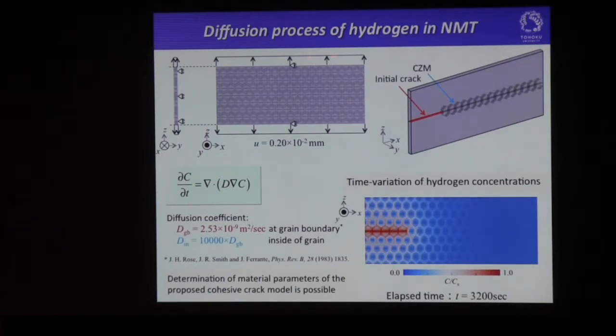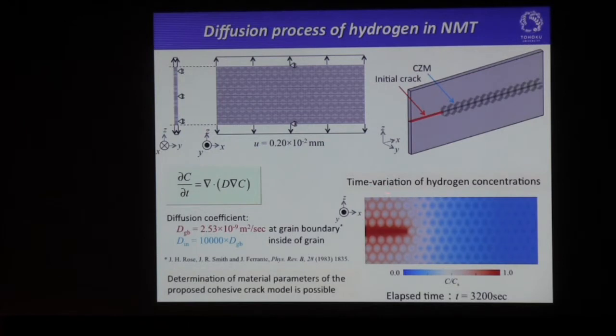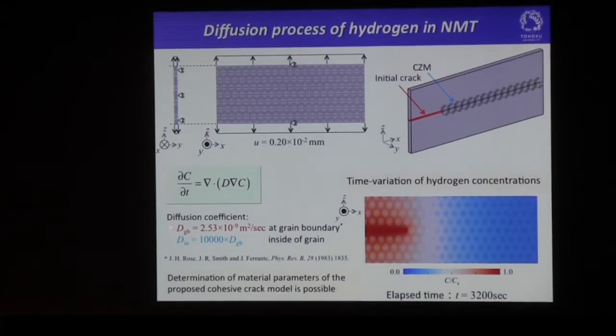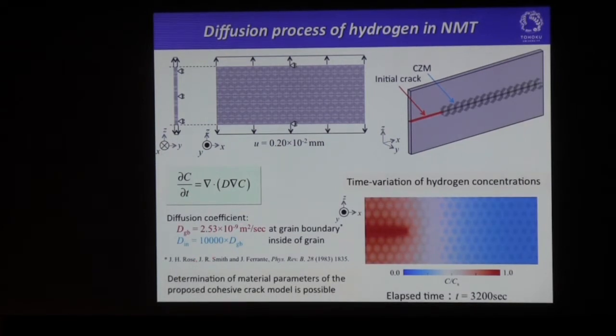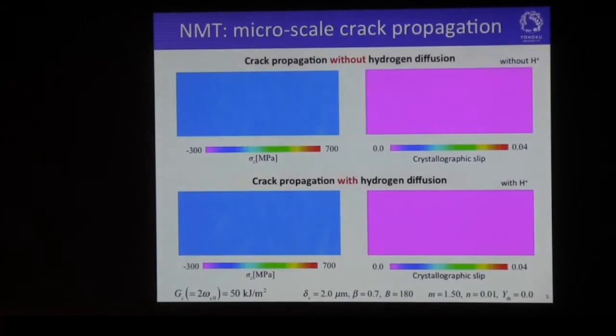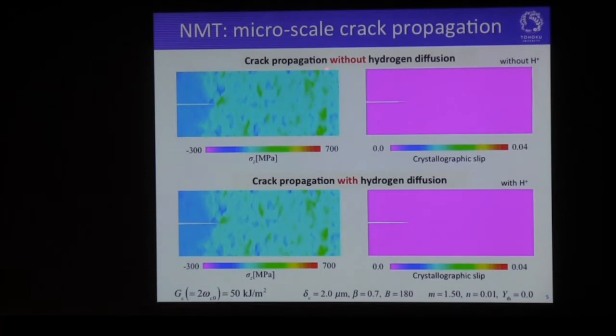Here shows the diffusion process of the hydrogen in the numerical material test. Here, this is the time variation of the hydrogen concentration. We used this diffusion coefficient that is borrowed from this article. With this time variation of the hydrogen concentration, we can determine the material parameters of the proposed cohesive crack model. Then we can conduct a numerical material test, that is the microscale crack propagation, like this.